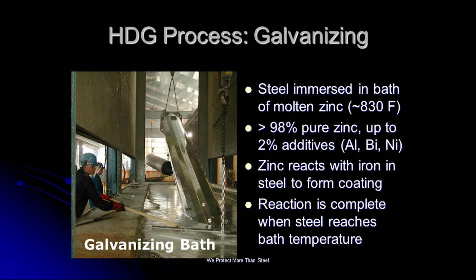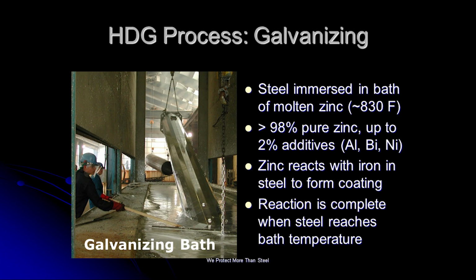Most galvanizing baths in the United States run anywhere between 830 and 840°F. To meet the ASTM A123 spec, they have to have a minimum of 98% pure zinc in their kettle. Some people add aluminum and bismuth and nickel for fluidity and reactivity. What ends up happening is you have this intermetallic of iron and zinc that actually forms inside the kettle bath. And then once the steel hits temperature, it's ready to come out.